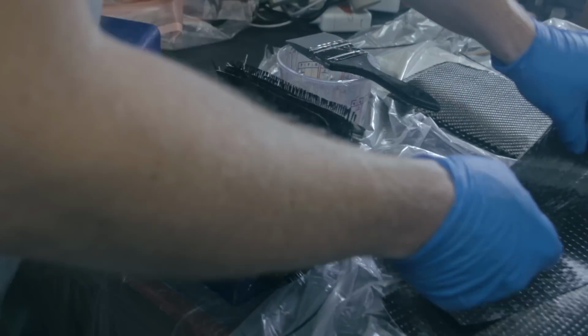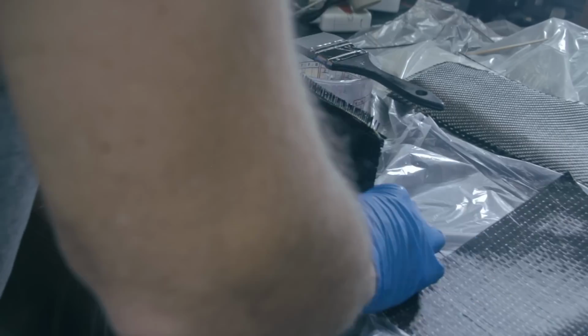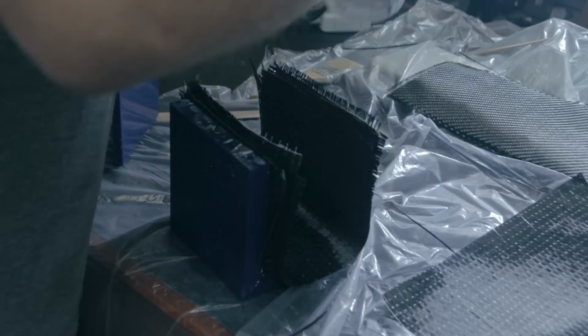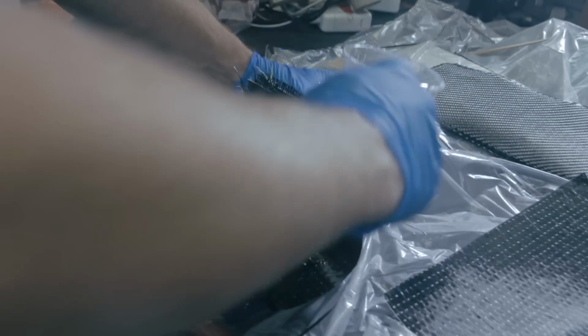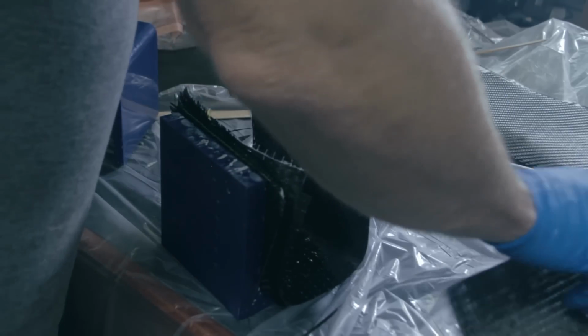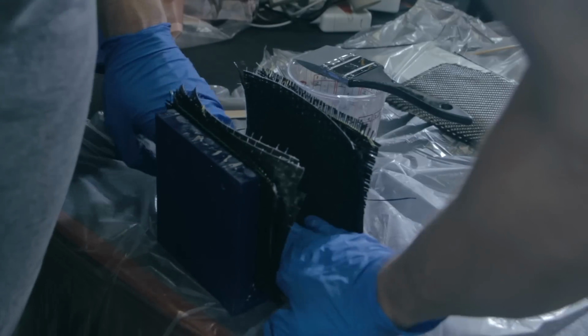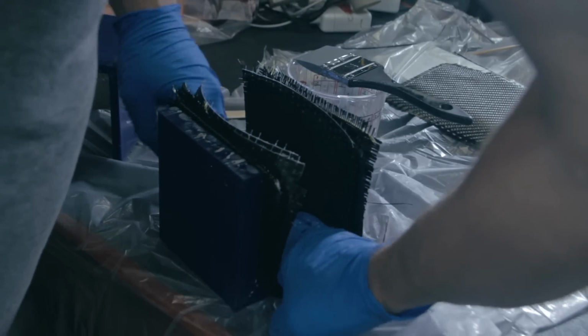So about now you can see my panic as I realize about 10 minutes in that this pot is starting to go off. In hindsight, at this point I really should have just mixed a new batch of resin and then calmly continued laminating. But that's not what I did. No, I did the braver thing. I worked faster and more sloppily. Here I'm just pouring the epoxy into the mold and slapping layers down as fast as possible. The epoxy is quickly turning into a sticky tar that is far more interested in adhering the carbon to my brush than to the previous layers.